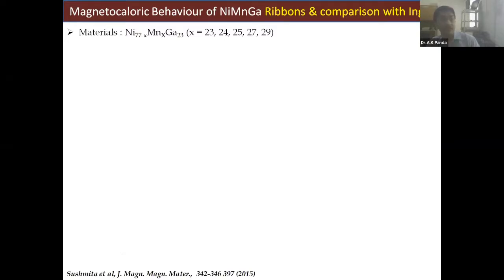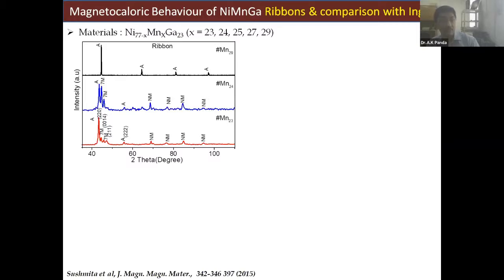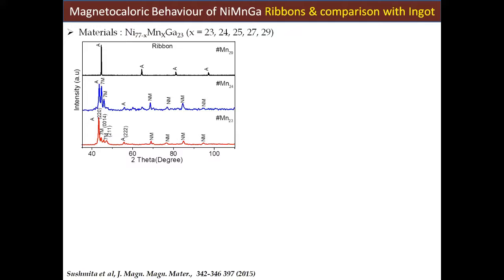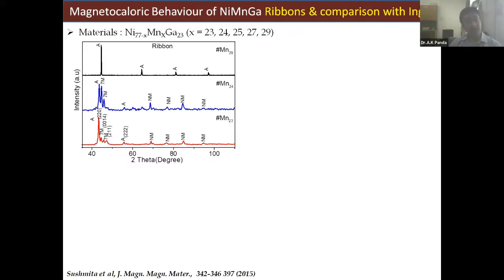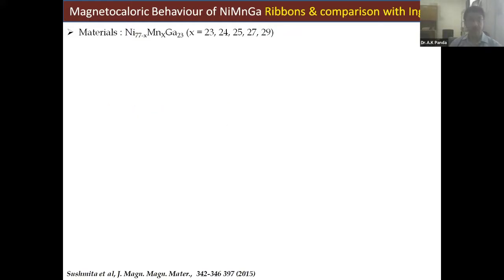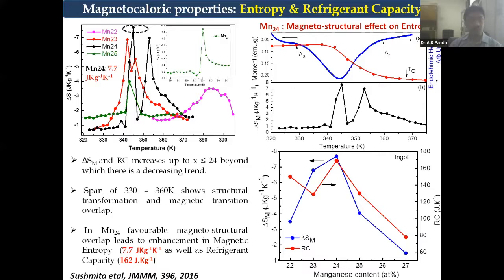And when we go for similar alloys, this is just to show you that when we go from low to high compositions, this is how you have more austenite. This is for the ribbon. Previously, what you found was for the alloy ingot, and the ribbon, as I told you, is melt spun on a rotating high speed copper wheel, and that gets you the ribbon. So this also shows fairly high austenite at high manganese content, and to show all the properties together, you find that a typical Mn24 shows, sorry,